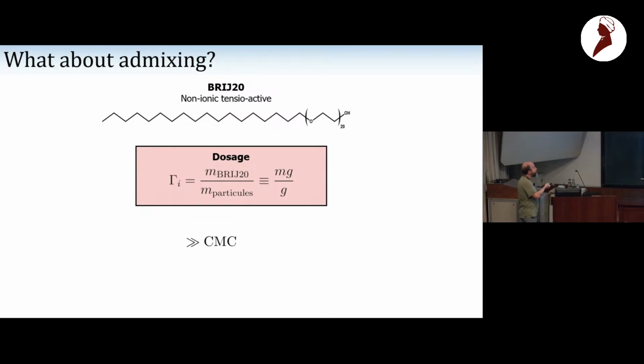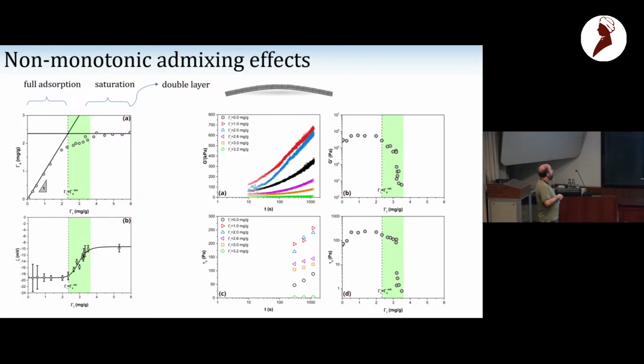And so we have studies ongoing in the lab where we looked at some polymers. This is one thing we started to do. We can go fast through that. This is the G prime as a function of polymer dosage. So you add a polymer here, which is a surfactant which will form a double layer. Eventually, if you completely cover your particle with the double layer, you will prevent formation of contacts. But if it's not fully covered, the double layer will move out, and the particle will find a way to form contacts.